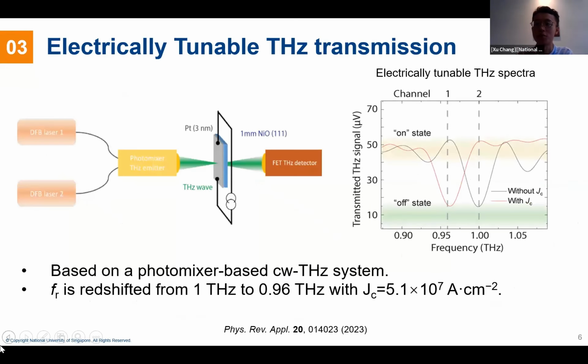After confirming the dominating mechanism, we used this to show electrically tunable terahertz transmission. This is a schematic of our experiment. We use two lasers with close frequency, and they go into a photomixer, which emits the terahertz. The terahertz is then transmitted across this sample and detected by our terahertz detector. When there's no current, at the right side it shows a dark peak around 1 terahertz. But with the current, the peak shifts to 0.96 terahertz.